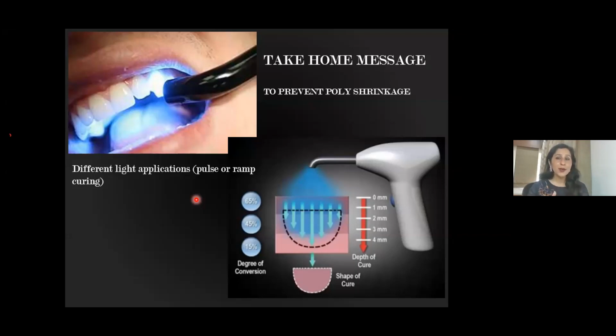And when it forms into a polymer, it does not go in a rush. It goes in a slow, intermittent fashion. So what happens? The stresses are not imparted to the tooth, but the stresses are absorbed by the polymer itself, by the composite itself. And then you can give more light intensity to fully convert the monomer into polymer. So what I mean to say is that first give less light intensity so that when the monomer forms into a polymer, the stresses that are generated are absorbed by the composite itself, and less stress is imparted to the tooth surface.